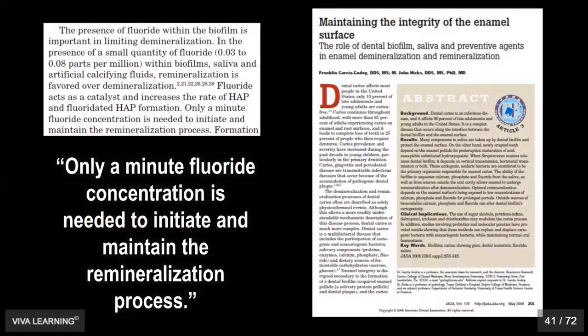But remember, we don't need gigantic amounts of fluoride to make a difference in a patient's mouth. You only need a minute fluoride concentration to initiate and maintain the remineralization process. What's a minute fluoride concentration? Well, according to Franklin Garcia Godoy and John Hicks in JADA, that minute fluoride concentration is only 0.03 to 0.08 parts per million. So even that slow trickle of fluoride from the glass ionomer is enough to shift the remin-demin balance in the dental biofilm, saliva, and in the enamel and drive remineralization rather than demineralization.